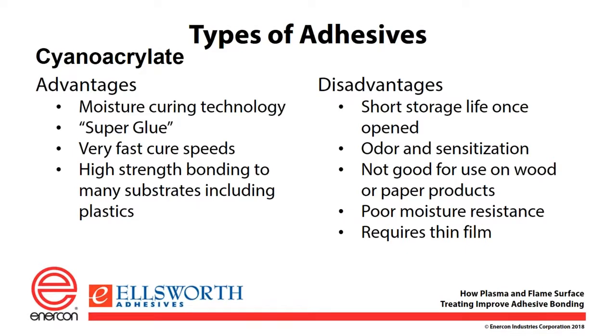Some disadvantages: once you open up the container, these have shorter storage lives because moisture will get into them typically when you start opening containers unless you're careful. They have odor, and they can cause sensitization in an industrial setting. They're not very good for wood or paper products. Once they're cured, they don't provide very good moisture resistance, and they require a thin film in order to get that fast cure. If you've ever worked with super glue at home, if you have a thick bead, that doesn't cure very quickly. But if you've ever put a bead between your fingers and squeezed your fingers together so it's a thin film, it bonds very quickly.